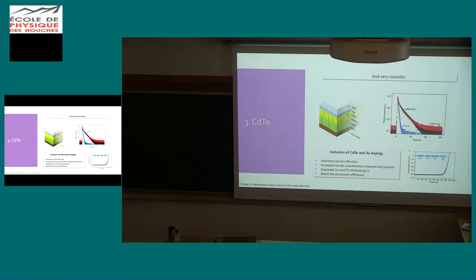The final improvement of cadmium telluride was thanks to the inclusion of cadmium selenide and arsenic doping in this material. Basically, they include some cadmium selenide telluride formation here that improves the collection a lot and reduces recombination because of increased carrier concentration toward the junction, and they really boost efficiency using this selenium treatment together with arsenic doping. This is a relatively secret process because it was developed by First Solar, a company, so they don't really display too many details about this.